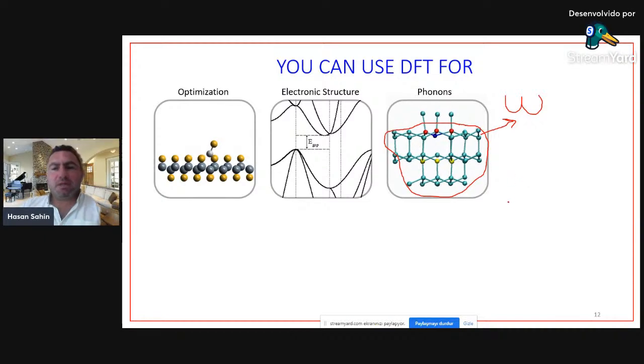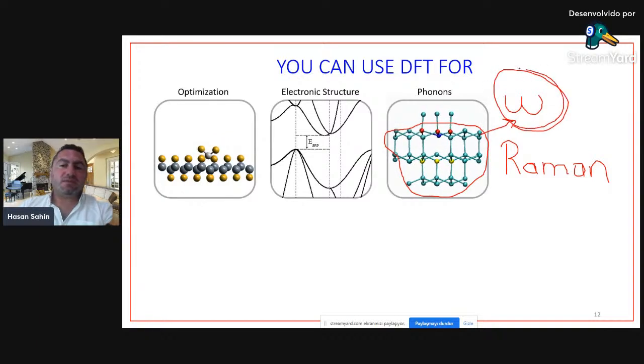And experimentally, if you have a Raman spectrometer, you can observe this phonon mode if it is Raman active. And maybe your phonon mode is not Raman active, and maybe it's infrared active. Then you can detect your phonon modes by using an FTIR spectrometer.